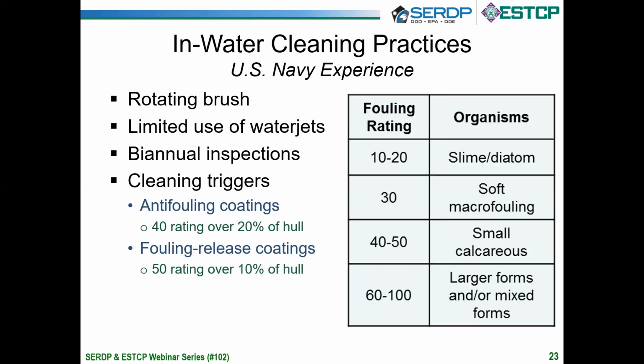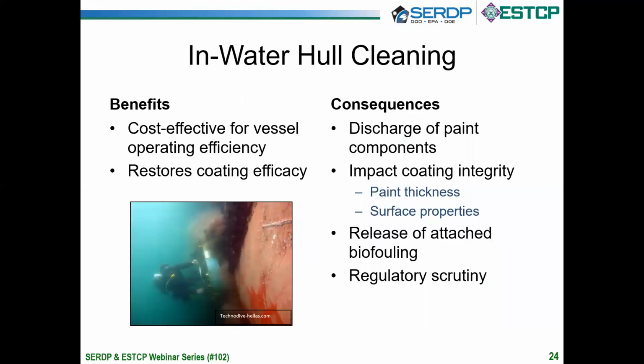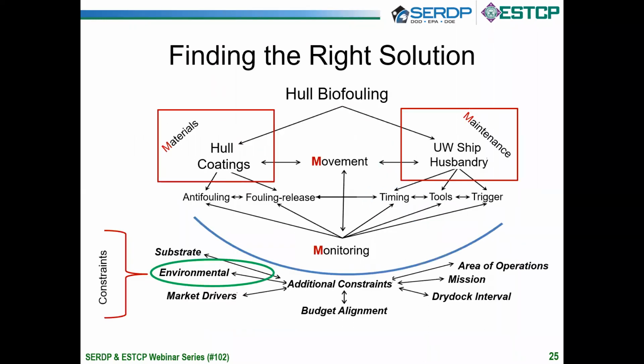Slide 24. The benefits of in-water cleaning I've already described, removing the biofouling as well as restoring coating efficacy. But there are these consequences: the discharge of paint components, the impact on coating integrity, especially paint thickness, and for fouling release coatings and brush tools in particular, a negative impact on surface properties. So slide 25. So we need to find the right solution.